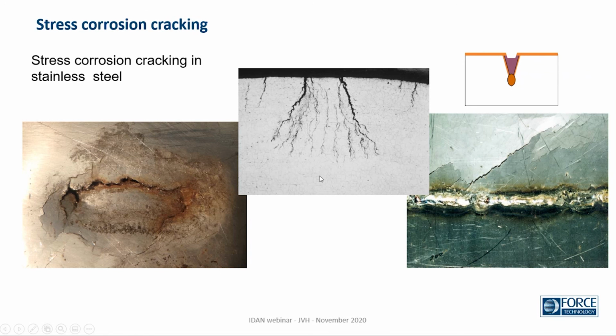And the relation to welds is perhaps not so obvious in this one. We have a weld, not a very pretty one, but just still a weld, and we have cracks going out from it. But in this one, it's very obvious that it is the weld stresses. There is a stiffener welded to the outside, and we can see how stress corrosion cracking forms around the stiffener at the weld, and it goes both around and perpendicularly to it, out into the base material.